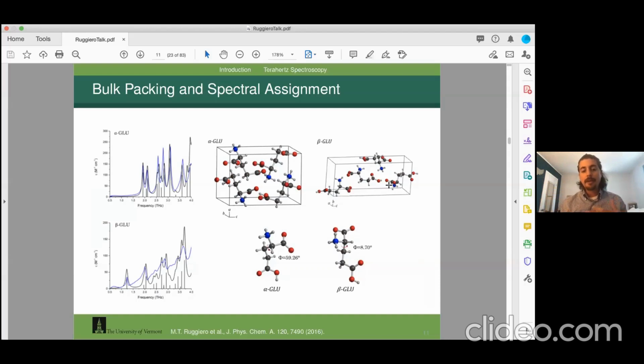And so the way we get around that and the way we address it is we do computational modeling, and we do density functional theory and quantum mechanical simulations, which are these black lines on this spectrum. And so what you see is if we do this well, we get an almost perfect agreement with the experimental data.